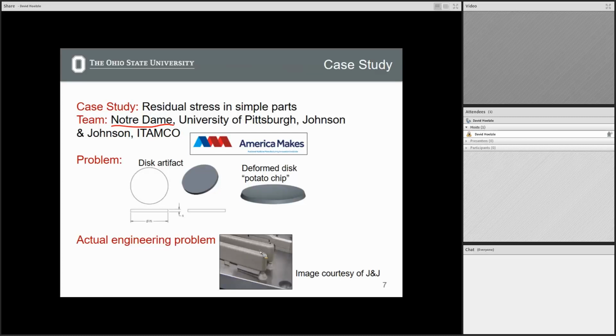These are actual parts that Johnson & Johnson would print. These are essentially handles that they'd have for their different manufacturing operations. And here's a direct result of too much residual stress in the part. The worst thing you can do with additive manufacturing, which is very much a big problem that they're trying to solve, is trying to make long, slender parts. It's pretty good at making things that are somewhat the same dimension in all directions. If you try to make long, slender parts, you get a lot of residual stresses in this direction, which then cause the bending or pulling up of this part, and then this is breaking away from the build plate.